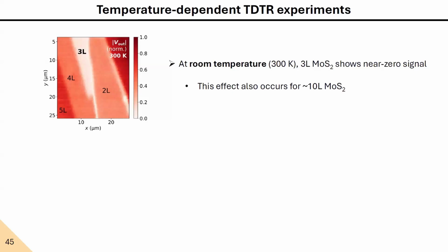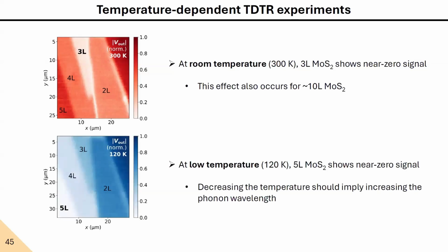So let's perform temperature-dependent time domain thermoreflectance experiments. We've seen that at room temperature, our 3-layer region shows barely any signal, and this effect also happens for around 10 layers. And when we decrease the temperature down to around 120 Kelvin, the region that shows no signal is not the 3 layers anymore. Now it is a thicker layer. Specifically, 5-layer molybdenum disulfide shows near 0 signal at low temperatures. Our intuition says that decreasing the temperature should increase the phonon wavelength, and therefore these resonance conditions should be satisfied on a thicker material region.